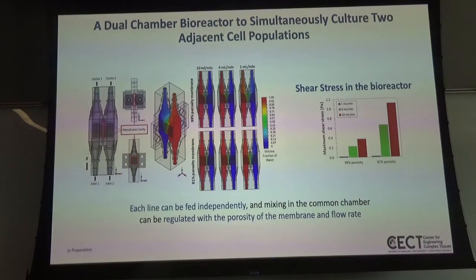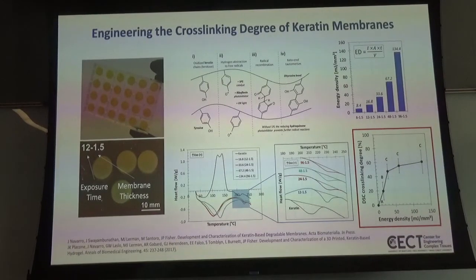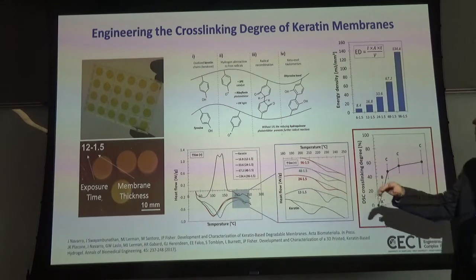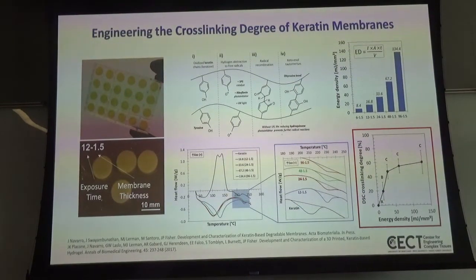So building that membrane took a little bit of time since we were working in a dermal application, and we had a nice collaboration with a company from North Carolina that did a lot of work in keratin-based materials. We decided to build a keratin membrane. This membrane is photo cross-linked using a printing approach, and the printing chemistry strategy is just based on riboflavin, which is relatively common in the field. So Javier made the observation that based on two key factors, the amount of light exposure time, as well as the thickness of the construct, so how thick the membrane was, you essentially could use those to control the amount of energy that was imparted in the cross-linking of that membrane, and then ultimately the stiffness or cross-linking of that membrane.